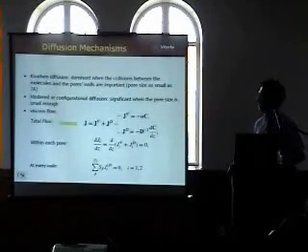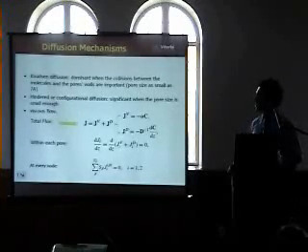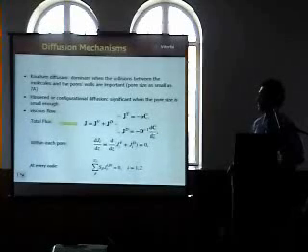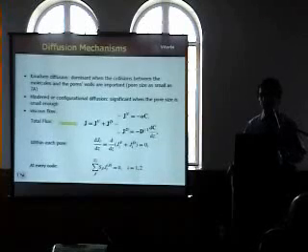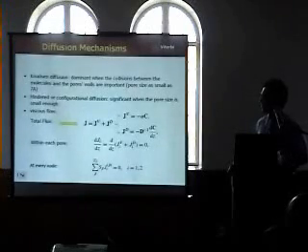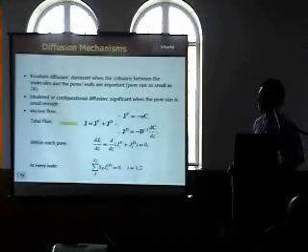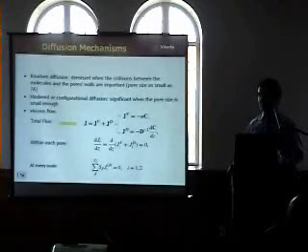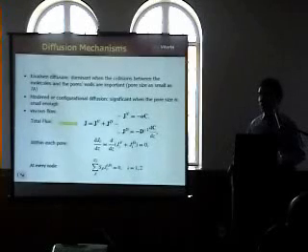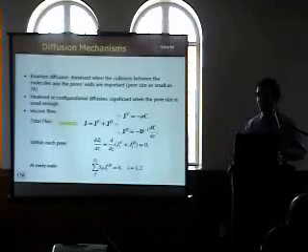We considered Knudsen diffusion as the dominant diffusion term, where collisions between molecules and pore walls are important — significant for the smallest pore sizes. We also considered hindered or configurational diffusion, which is significant when pore sizes are even smaller. We studied viscous flow as well, but the simulation shows that viscous flow doesn't contribute much to transport unless the pore size distribution is broad enough.